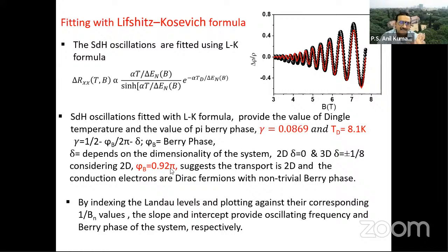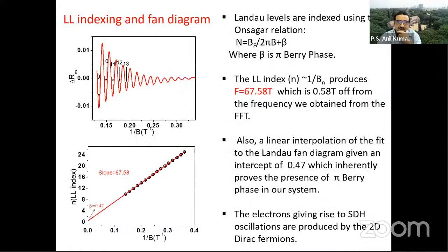So, if I have error bars added to it, then you will see that it is approximately pi. So you are getting a pi Berry phase. The pi Berry phase is also giving you an indication that you have Dirac electrons in the system. So it's a two-dimensional nature of transport and the Dirac electrons in the system with an effective mass which is 0.14 kind of thing.